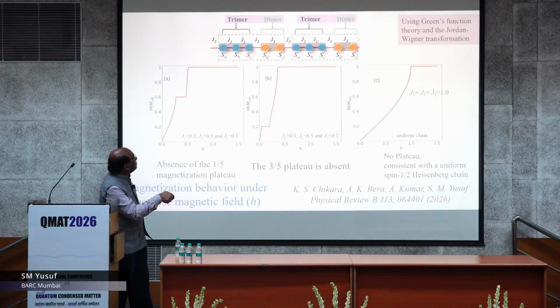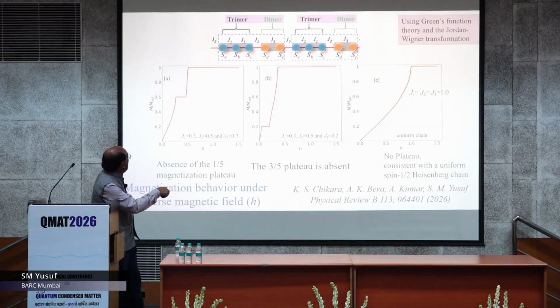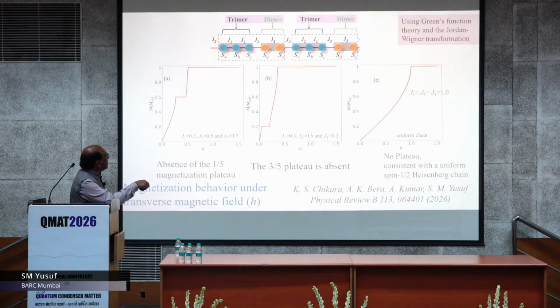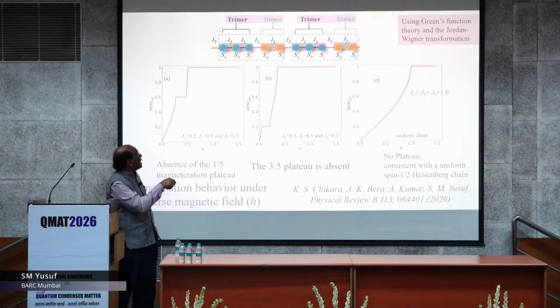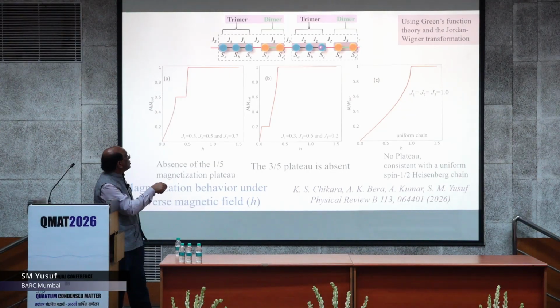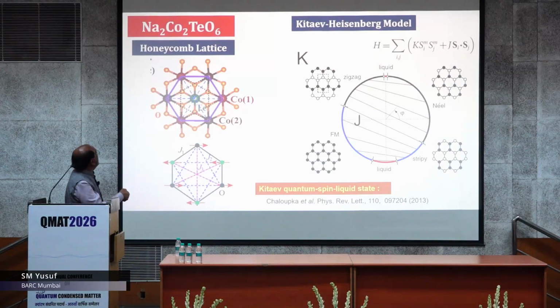If this is a uniform type, all the same, it is like a uniform magnetic chain, so not interesting enough. But we can have this 1/3 magnetization plateau. We can have not only 1/3, but 1/5 and 3/5 magnetization plateaus, depending upon this J3, between the dimer, what is the exchange constant strength. So one can design this kind of novel system, and there is a possibility that experimentally we will be able to verify this. This is for the last example.